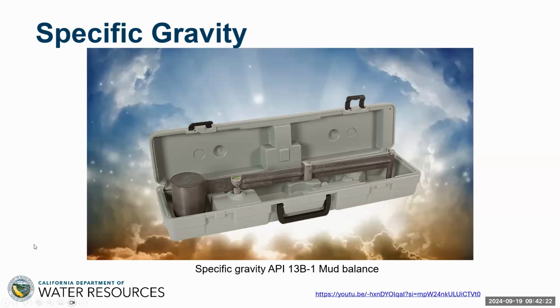Now, why is that important? Well, when we think about it, the main components in the grout are water, cement, and probably sand. And the SG is very driven by the actual amount of these major components in the mix. So if you, for example, had a typical neat water cement ratio grout, say 0.5, you would be targeting a specific gravity, maybe 1.8, something like that.